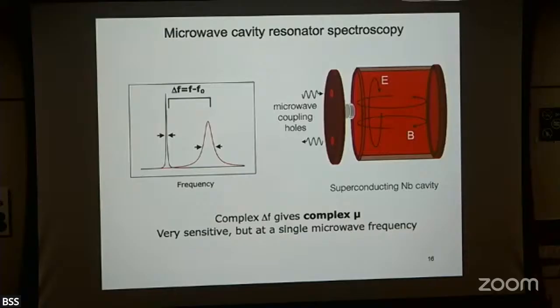Can you also see that the peak is broad, that the shape is changing in other ways? It's not just the shift in the peak, but the shape too. In principle you could, but that is typically a sign of something going wrong with your experiment, in the sense that you're overcoupling. In order for this formalism to work, you really need to be in the limit of infinitesimal coupling.